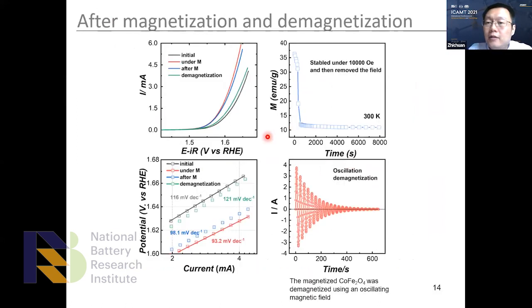And then we did other measurements, for example, magnetization and demagnetization, right? We measured activity under magnetization, and we observed the increment. And then what if we remove the magnetic field? Let's say the materials will keep their magnetization to a certain degree, right? And we can see that this blue curve is maintained for a while. And then if we do a demagnetization, for example, using thermal interruption or an oscillation demagnetization process, we can observe the activity drop back to the initial state. So this confirms the increment is due to the magnetization of cobalt iron oxide.